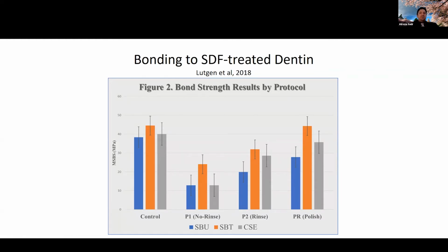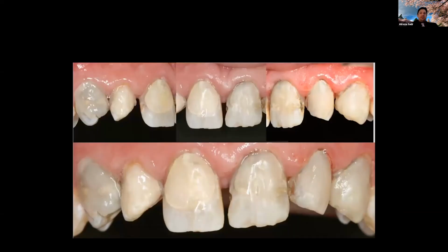And I highly recommend that you look at glass ionomer for covering of the SDF treated dentin. If you go ahead with the bonding agent, I think using a total etching technique, even though I totally believe in self-etching technique, but if you're dealing with silver diamine fluoride, because of the alkaline nature of this material, you do want to bond, definitely do a total etch, do a phosphoric acid cleaning before you go ahead with application of your bonding agent.